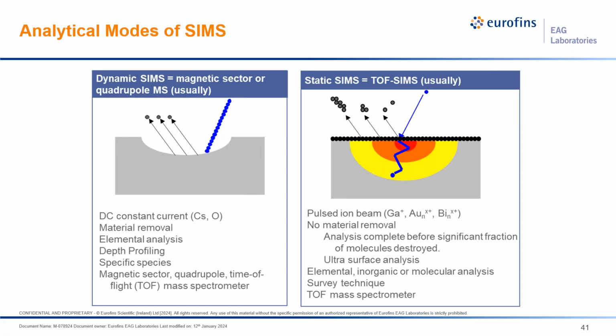The final technique, time-of-flight secondary ion mass spectrometry, can be run in both static and dynamic SIMS modes. As Alan pointed out, he is a dynamic SIMS specialist. But when you take the initial strike of one ion on a surface, that is a static SIMS experiment. We are at a point where we're not actually etching away the surface yet. We're still hitting the outer surface and looking at ideally intact areas. And from that, we have secondary fragments and more molecular ions available. So we keep that dose very low. We can just probe the surface without actually completely consuming and then etching the sample. So that's the realm of when we go from static to dynamic SIMS, is just a somewhat arbitrary value of dose to the sample.